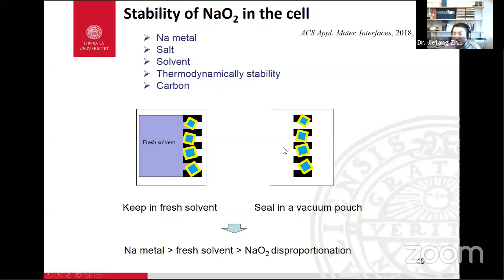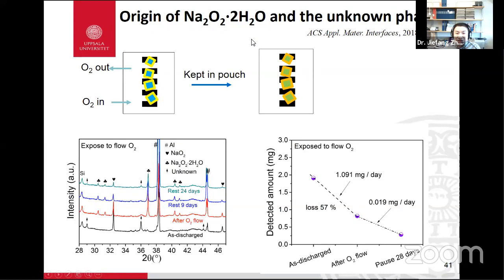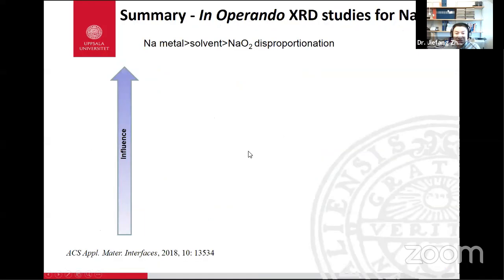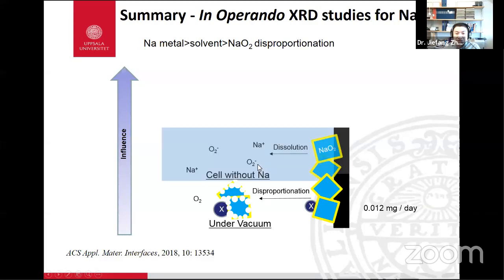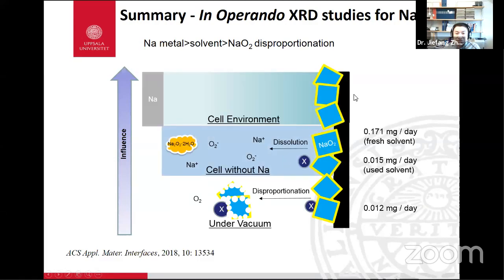Also, the solvent has an effect, and the self-disproportionation also has an effect. We found some sodium superoxide hydrate and an unknown phase, connected to the oxygen feeding, because of the trace amount of water that we found. By the XRD measurement and quantitative analysis, we found the main problem is the sodium, because the sodium superoxide dissolved in the solution, but then continuously reacts with the sodium, which makes this fast decomposition.